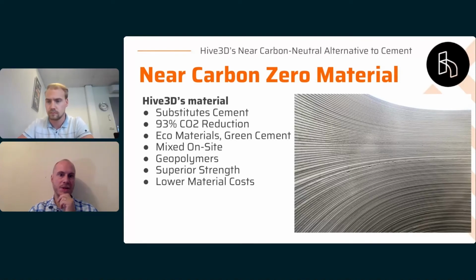It's not a structural issue with the way we build our houses, because we fill our walls solid with a different carbon-friendly concrete. But we had some cracking initially. We've been able to almost 100% eliminate the cracking by using some fibers. So we have some PLA fibers that we mix in now, and those fibers add strength, and they have pretty much eliminated the cracking. Perfect.